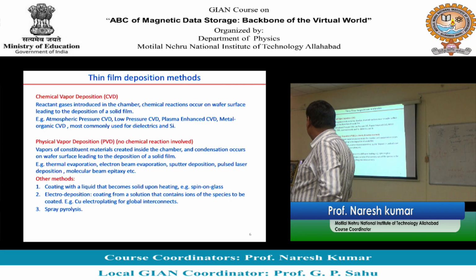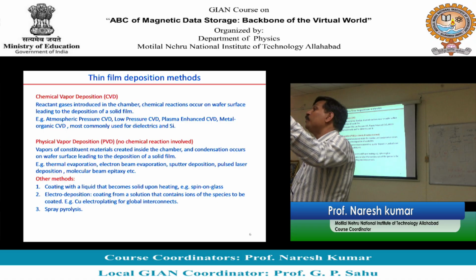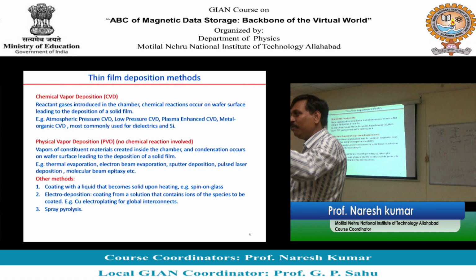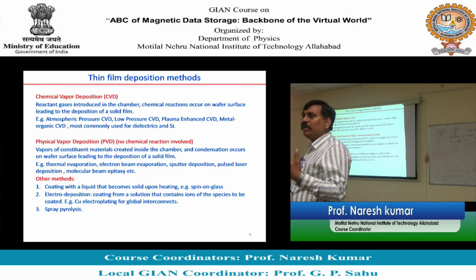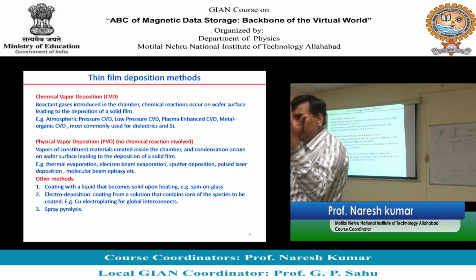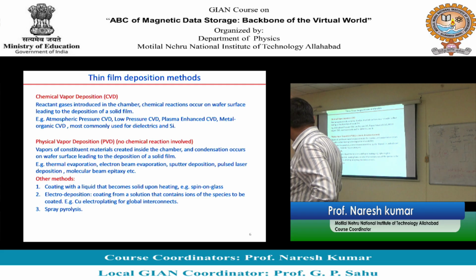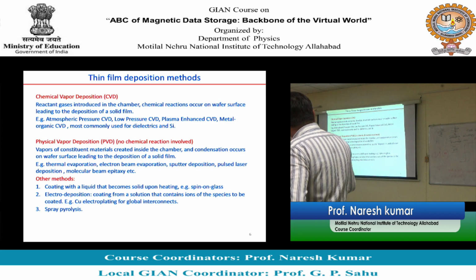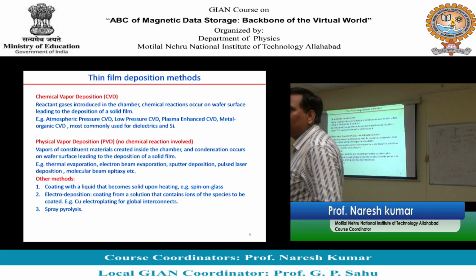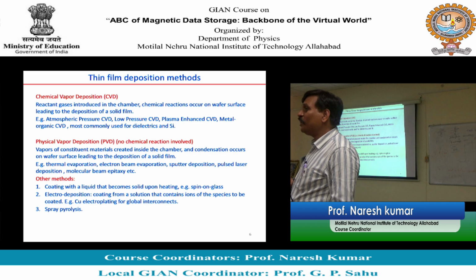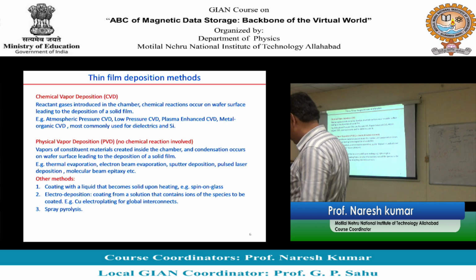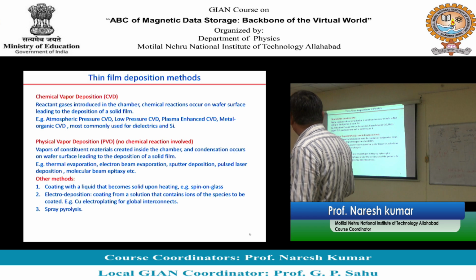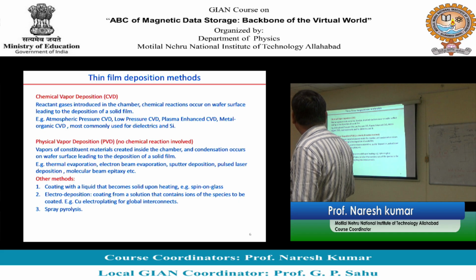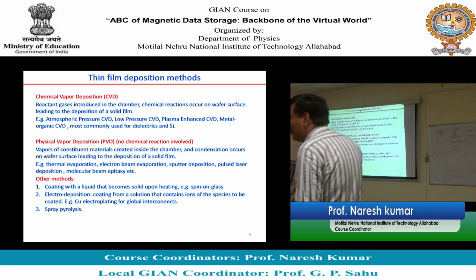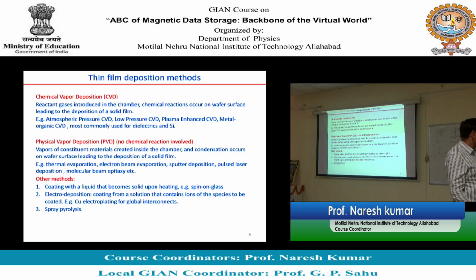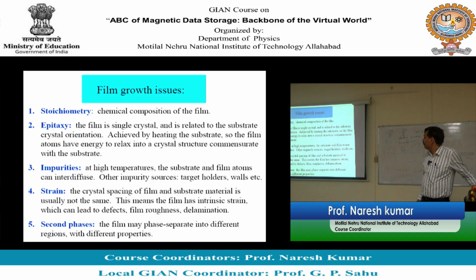It depends. When you use spray pyrolysis, the film may not be too dense. You may have huge porosity. Suppose you want some film that requires some porosity, I think spray pyrolysis is required. So based on applications, you can choose the method. And as I said earlier, based on the resources that you have with you. So if somebody can afford to have MBE, I think the best is you can have MBE with you. But it's very rare, it is difficult.